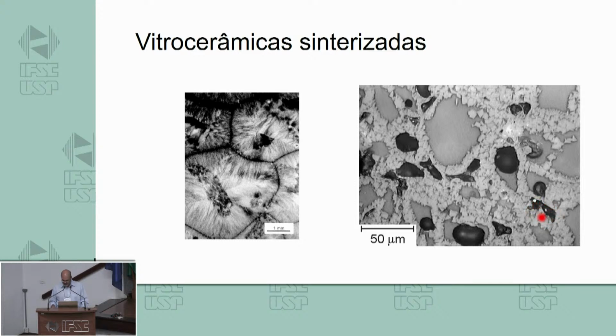These are trapped pores due to the surface crystallization, but as the density of the crystalline phase is very much higher than the glass phase, you have spherical pores inside each particle. This is difficult to avoid. If you're lucky to have the same density, you don't have this problem. But in general, the crystalline phase is denser than the glassy phase, and some intensity of this problem you may face.